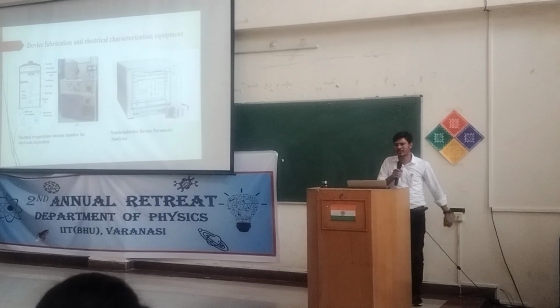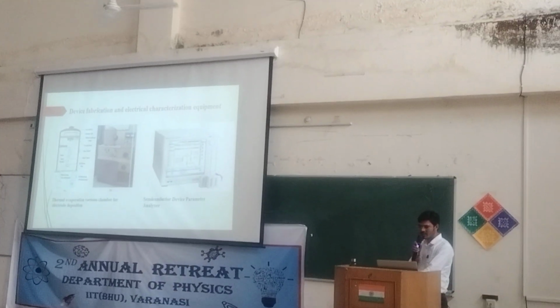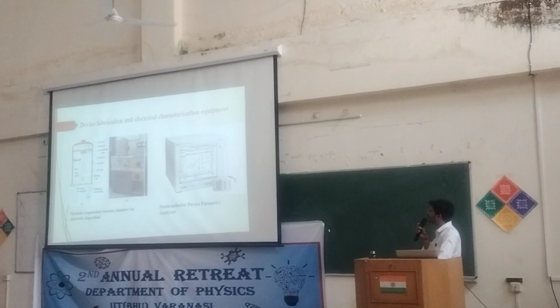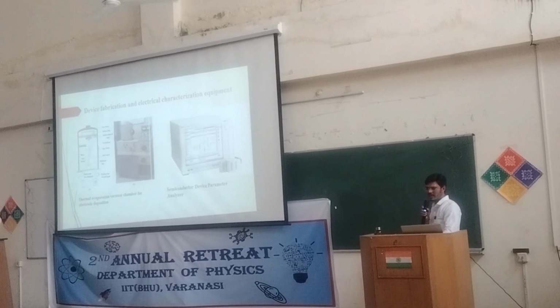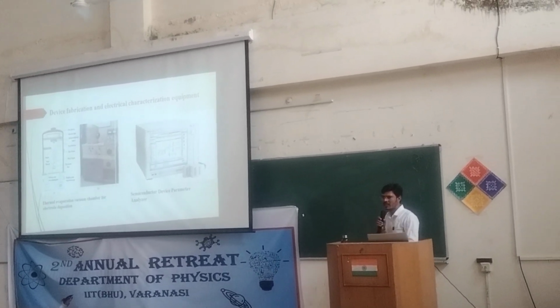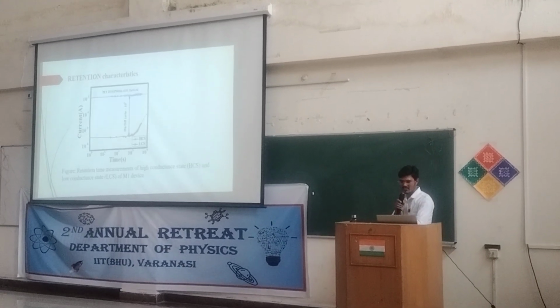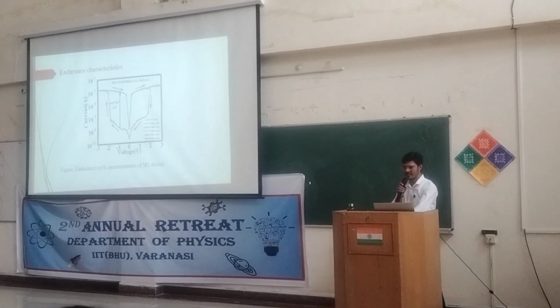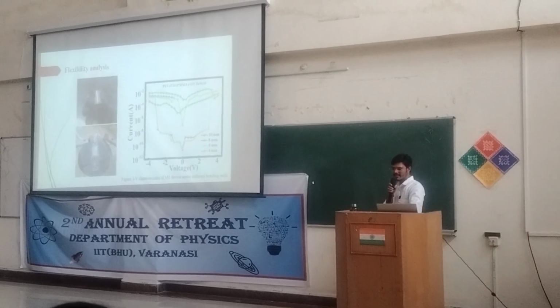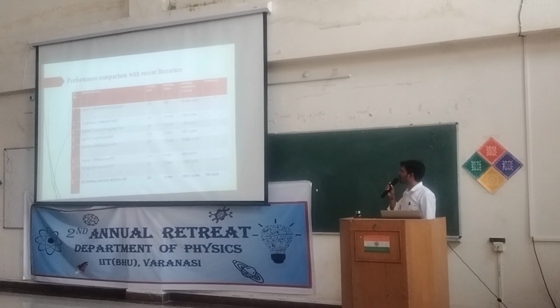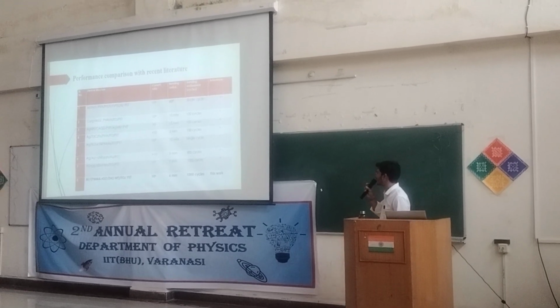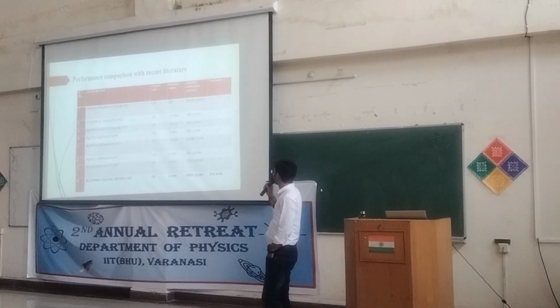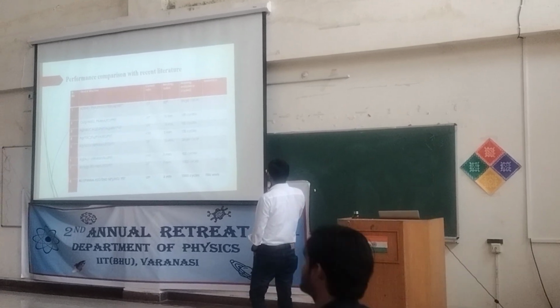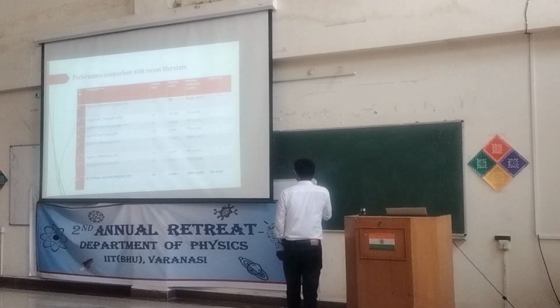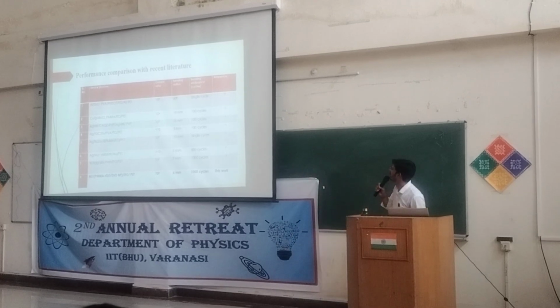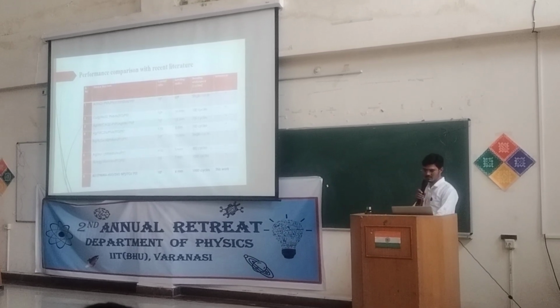These are two different instruments that we have used: a thermal evaporation vacuum chamber for depositing the electrode, and a semiconductor device parameter analyzer to measure the different parameters. He measured endurance and retention characteristics, and also the flexibility analysis, and he performed this experiment with a minimum bending radius of 6 millimeter, effective for 10 to the power 4 seconds and 100,000 cycles, and the current ratio is 10 to the power 6. Thank you.